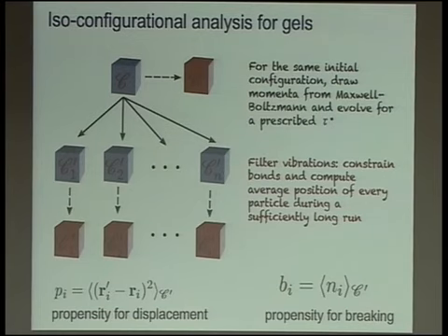By doing this, you can look at the distribution of each particle's displacement over this sample. Because the particle configuration is exactly the same, it's the velocities that have been changed across this sample. Then I get a spatial distribution of displacement, and I can try to map this back into information like: this initial particle that was in this specific part of the structure, is it likely to move more or less after a certain time? So I get a spatial distribution of how heterogeneous the dynamics is in the system, and I can try to connect this with what I know about the structure.